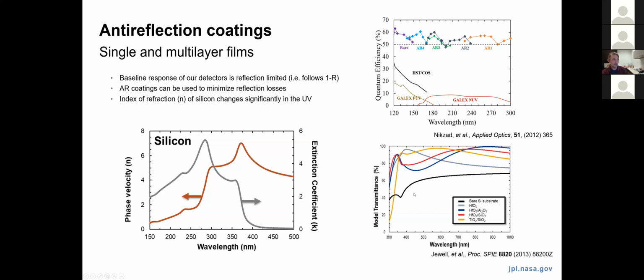And then there's sort of an easier job of it, if you will, as you move to longer wavelengths, because as you can see, the refractive index becomes more uniform. And so for near UV, visible, near infrared options, we can consider fairly simple AR coatings like single layers of hafnium oxide or simple double layer filters that give quantum efficiencies in excess of 80% across this wavelength range.